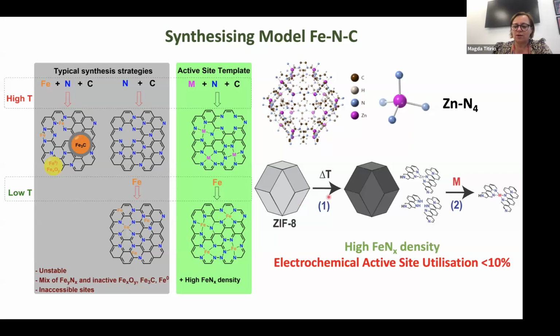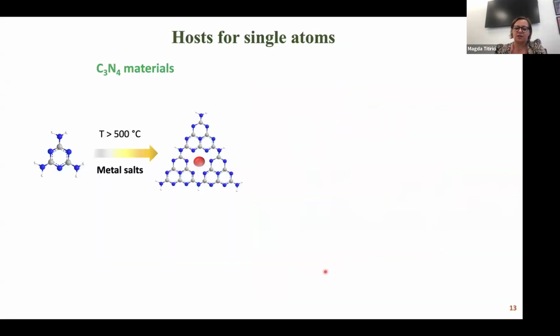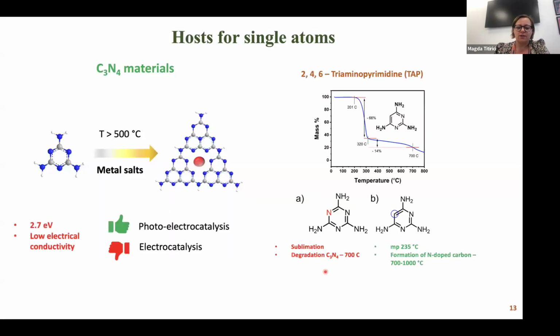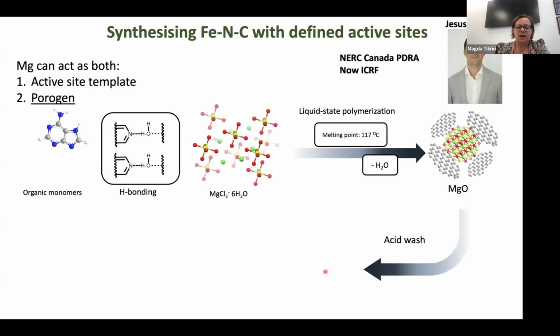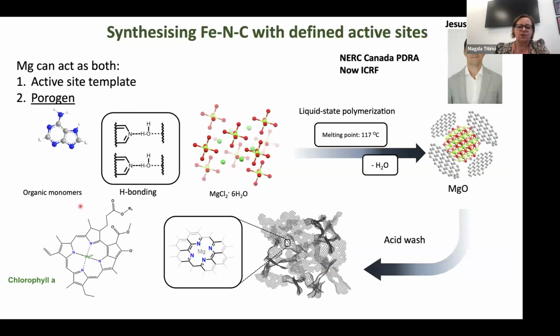However, when you carbonize this ZIF-8, which is a MOF, you would collapse most of the pores. You would get a relatively high iron nitrogen single site density, but because of the microporosity, you would not have access to these active sites, and you'll get a poor electrochemical active site utilization. I will skip this slide and tell you the way we did it.